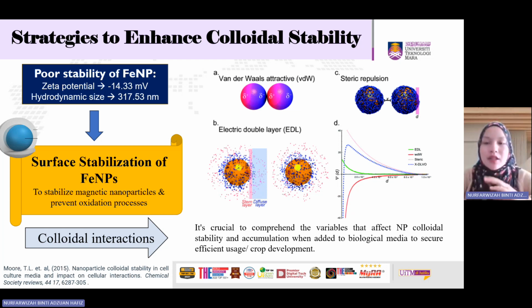Theoretically, the zeta potential on the nanoparticle surface shows that the particles are persistent. With higher negative or positive zeta potential, the nanoparticles tend to repel one another and reduce the aggregation. In general, it is anticipated that a zeta potential value beyond the range of 30 millivolts has enough repulsive forces to improve the physiological stability.